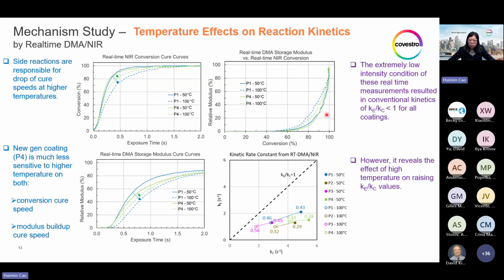Very different from what we are showing from the draw tower simulator. We actually also anticipated this because these real-time methods are at extremely low intensity. They are at milliwatts level, so nowhere comparable to the actual fiber drawing conditions. Nevertheless, this experiment does show the temperature effect from 50 to 100 degrees C, where the direction of these arrows points, the ratios of Ke over Kc, which are labeled here, are all going slightly higher.